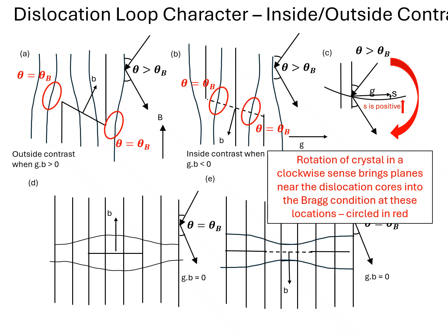For this particular condition, S is positive and we have weak diffraction, but when the planes rotate, the diffracting vector, known by G, also rotates. We're rotating the normal to the plane, and we bring it in coincidence with the Ewald sphere, and then we get strong diffraction. So I've stated that here so you can picture that.